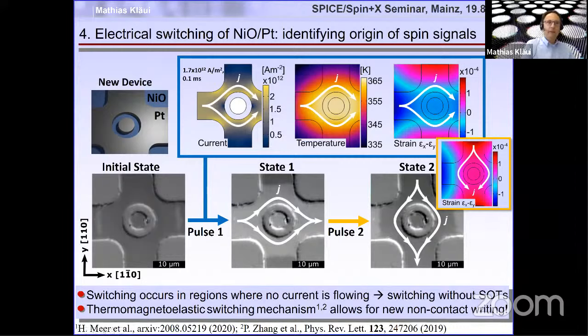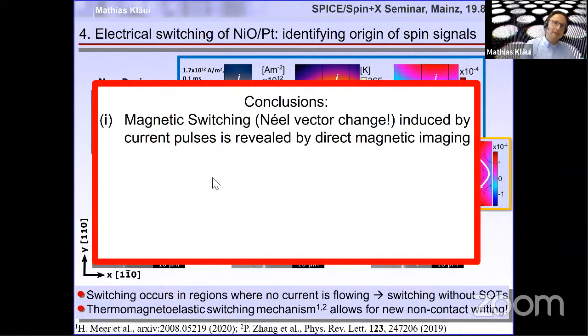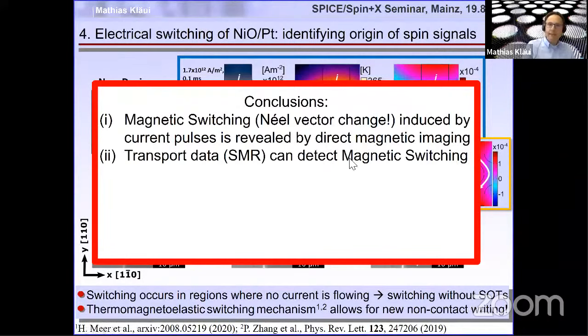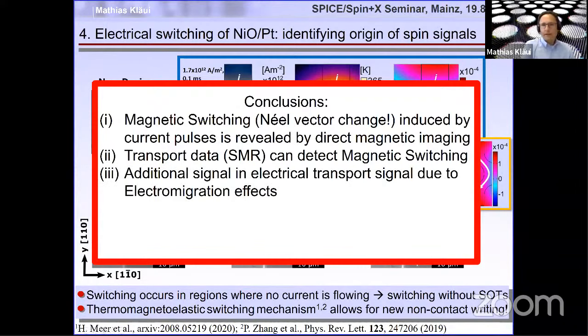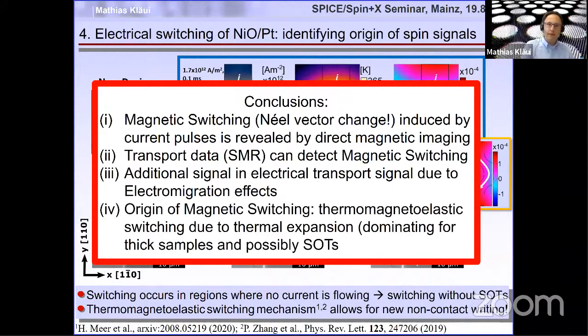So the conclusions of this part here, which is kind of the new, is that the magnetic switching is induced by current pulses that can be revealed by direct magnetic imaging. So there is magnetic switching. Transport data can detect this magnetic switching if you appropriately subtract these electrical effects. There are additional electrical effects due to electromigration. And the origin of the magnetic switching in the thick samples at least is thermomagnetoelastic. And there are possibly also spin orbit torque effects primarily in the thinner samples.